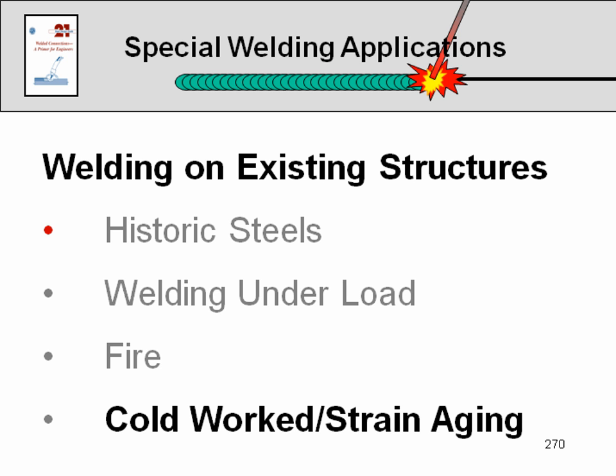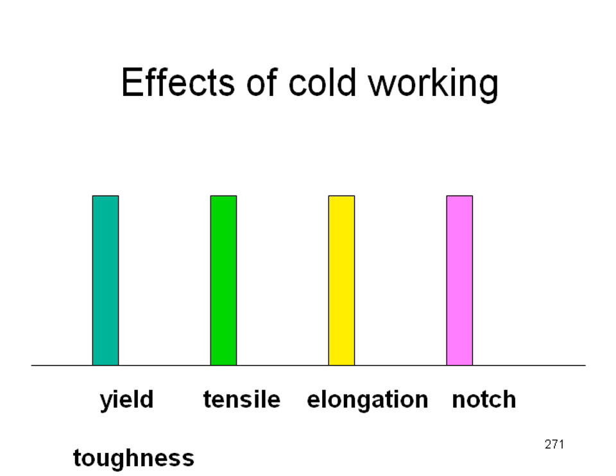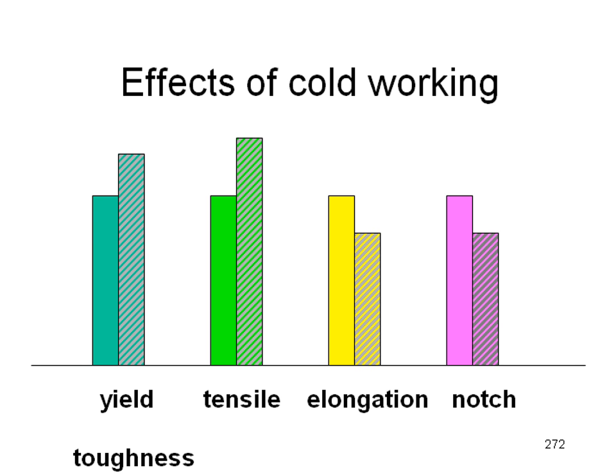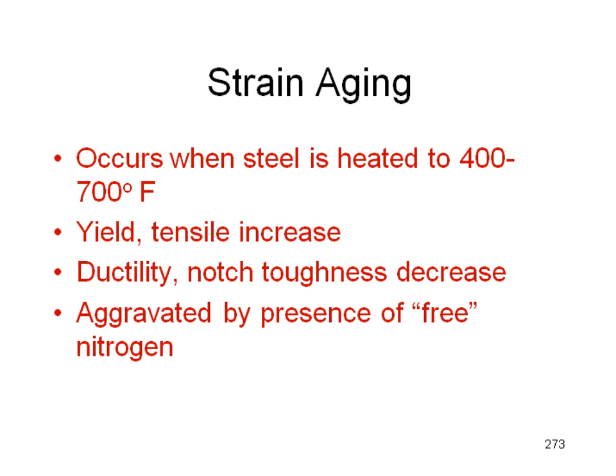Now, the next issue we have is that of welding on cold-worked material and strain aging. Many times we're dealing with structures that have been deformed due to service loads or natural forces. Overload conditions, hurricanes, maybe even seismic events, we could find ourselves welding on cold-worked material. Now, these bars represent the properties of hot-rolled steel. When we cold-work steel, we increase yield and tensile, but we decrease elongation and we decrease the notch toughness.